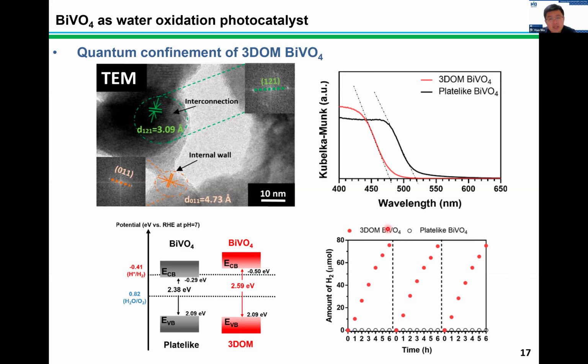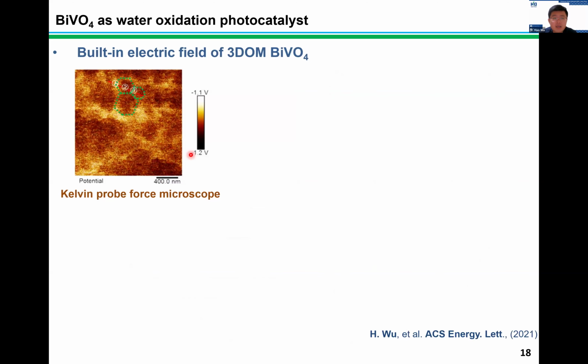And upon that, the second fine structure analysis that I would like to share is about the distinct lattice structures between the interconnection part and the internal wall of the 3DOM bismuth vanadate. I've introduced in the introduction that crystal engineering is one of the general strategies in manipulating charge transport of semiconducting oxide. So we were wondering if there is a potential energy gradient between the interconnection part of bismuth vanadate and also the internal wall. To prove that, we did the Kelvin probe force microscopy, KPFM, and we did a line scan across the interconnection, the wall and the internal wall.